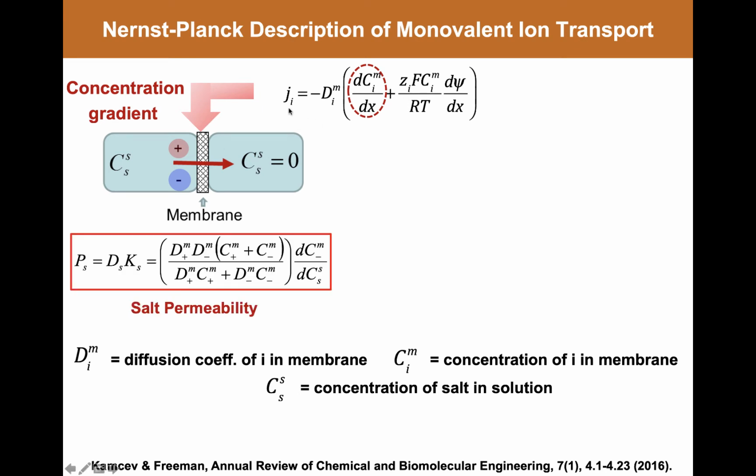Now, you can apply the Nernst-Planck equation to this case with these field-driven terms set to be no net electric field across the membrane, and you get an expression for the so-called salt permeability that is shown here. And deriving this expression relies on the fact that a really important, fundamental, and very powerful force in electrochemistry is the concept of electroneutrality. Nature simply will not allow much of a charge imbalance to build up in either of these solutions or inside the membrane.